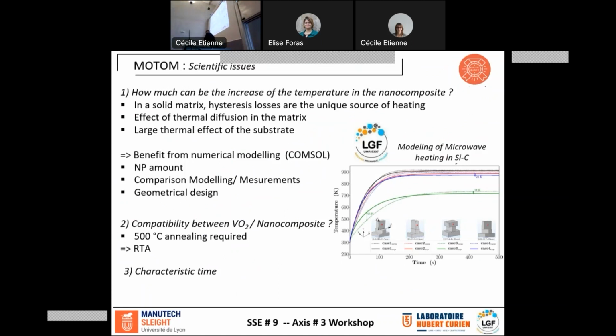So this is why we think that we will really take benefit from the modeling, which will be made using firstly COMSOL. And this is the experience of our colleagues in the laboratoire Charles Friedel. We were able, for example, to model the microwave heating in the silicon carbide. So they are able to model the elevation of temperature as a function of the time. So they have a large experience on that. And we think that it is really important for us, for example, to design how much nanoparticles we have to use in the matrix, of course to compare this modeling to the measurement done before, and also finally to do the geometrical design of the device.